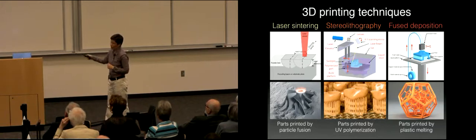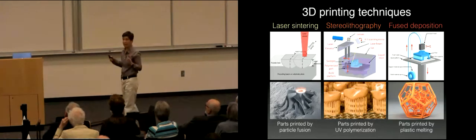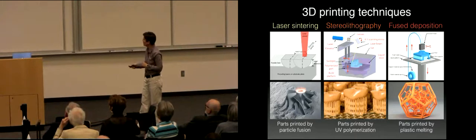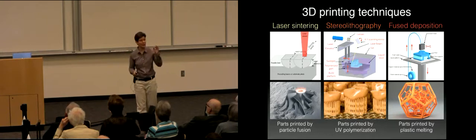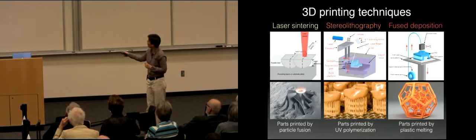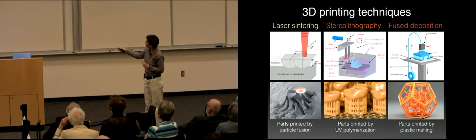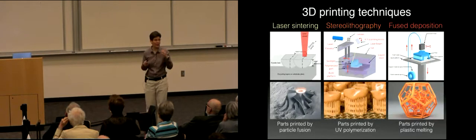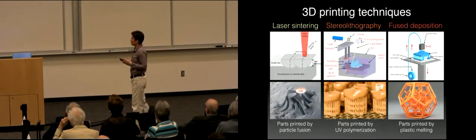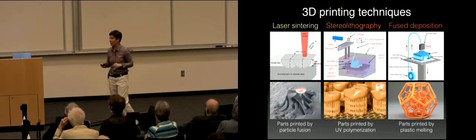These are support structures that have to be removed from the shell before you use it. And this is just a printed part out of an FDM head where you're feeding in thermoplastic filament. And in order here, you have to have a support material. Here, the liquid resin, and these features are support material. Here, the powder bed is a support material. You always have to remove that support material. That's kind of cumbersome. So we've developed a printing process where you need no support material, and I'll describe that in more detail.